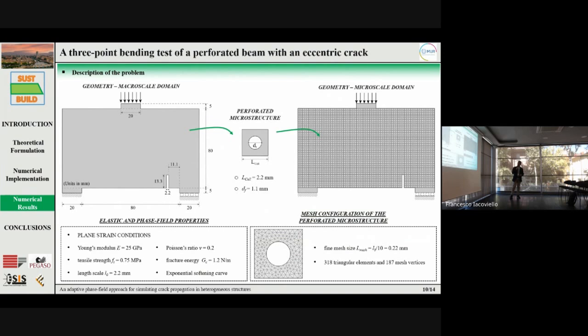The second example involves a 3-point bending test of a perforated beam with an eccentric crack. Starting with the geometry of the macroscale domain, the beam has a length of 140 millimeters and a height of 80 millimeters. On the right side, instead, we see the geometry of the microscale domain, where each perforated microstructure or microsubdomain consists of a square shell with a centered hole. The elastic and phase field properties are the following. In this case, exponential softening curves are used to capture material degradation during the crack propagation.